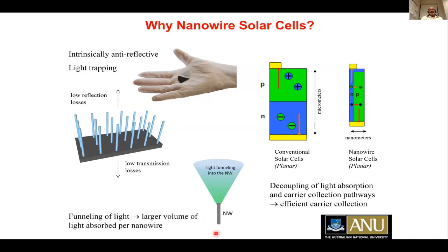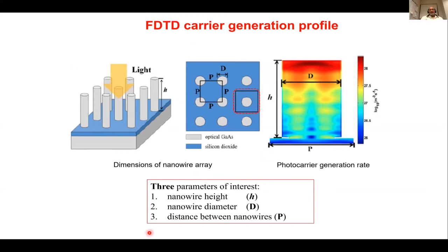Also, these nanowires act like light funnels, so they also act like light concentrators, which makes them very attractive. Again, we have done a lot of simulations looking at what the height of the nanowire should be, what the diameter of the nanowire should be, and what the distance between the nanowires, or the pitch, should be. You can see that most of the current is generated at the tip of the nanowire, indicating that we don't need to make long nanowires. About 1 or 2 micron long nanowires are more than sufficient.